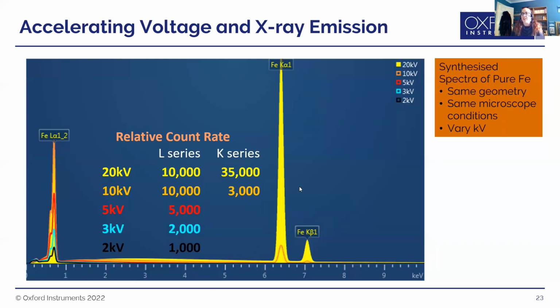And again, this is just comparing it. You can see the different spectra at the different accelerating voltages, and you can also see the number of counts. So these are the number of X-rays received at each of these. At 20 kV, you're getting tons of X-rays. Then as you go down to 10 kV, you can see the effect on the K series. The L series is still good. But as you drop further, you get much, much lower counts. And this affects the speed of your acquisition and the amount of information in your data.